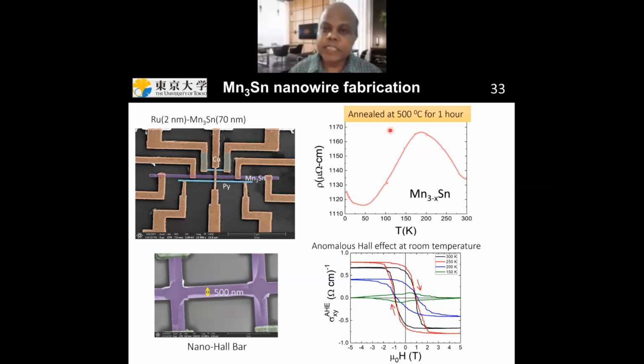And this is the temperature dependent resistivity of the nanowire, in which we deposit the nanowire at room temperature and anneal up to 500 degrees centigrade to crystallize. Also, if you measure the Hall bar just next to this device, you can see the anomalous Hall effect. And this anomalous Hall effect disappears below 150 Kelvin. That confirms that this nanowire is actually Mn3Sn and not something else.